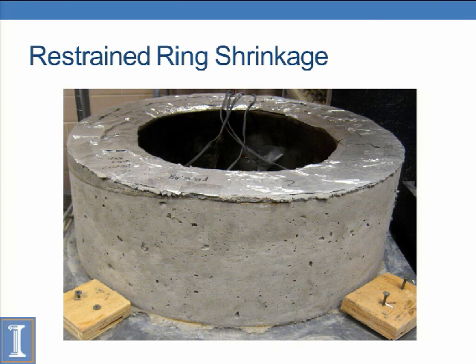Another shrinkage test we did is known as restrained ring shrinkage. With this test, you have an inner steel mold that's ½ an inch thick, and you have strain gauges attached to the inside of that steel ring. And then you have 3 inches of concrete cast around that steel ring. You seal the top, the bottom is sealed, so all your drying is on the outside circumference. So as the concrete dries, it shrinks, and you get strains on that steel ring.